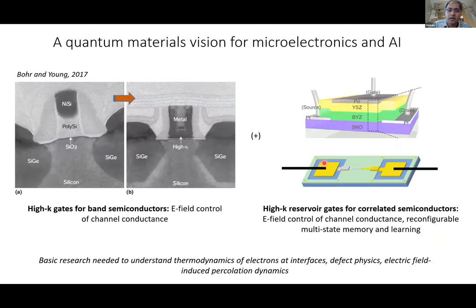And so this is the vision for microelectronics, or one vision we have for microelectronics. So if you are familiar with traditional transistors, you can see the big leap happened some years back. Silicon, silicon dioxide, polysilicon was replaced with silicon, high-k metal gates. And so this is considered a revolutionary change. And I think we can envision the next revolutionary change here, which is quite compatible with silicon, actually. We want to basically extend the concept of this high-k not just to sustain electric field and high capacitance, but actually high-k as an ion reservoir. So you need minimal modifications here.